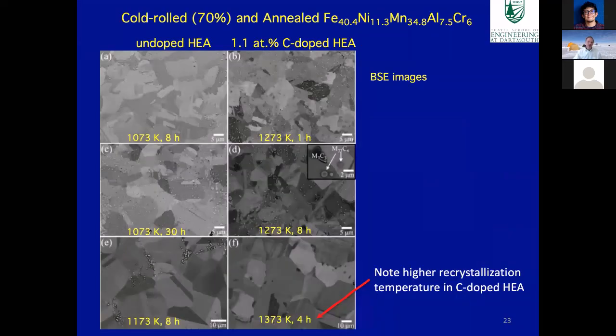So one of the things we've done with this particular alloy is to do some thermomechanical treatment. We cold rolled it to a 70% reduction and then annealed it. And we did this for the undoped alloy and the one with the highest carbon content. And there's a couple of things I want to point out from these images.